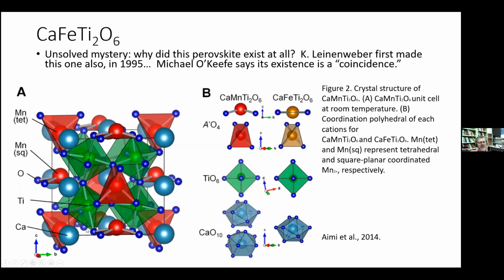And then the other one we found was a unique perovskite structure that had never been seen before. It has a space group P4_2/nmc. It's tetragonal, and it turns out it's a kind of a twin of that other phase I just showed you. So you get half of the iron in tetrahedral coordination, which is that red tetrahedron. There's the titanium framework, TiO6 octahedra, and then here's the square planar iron, but in this case, it's a little off the center. It's not acentric though, it has centers of symmetry in the structure, but this particular atom is off the center of the square a little bit. Okay.